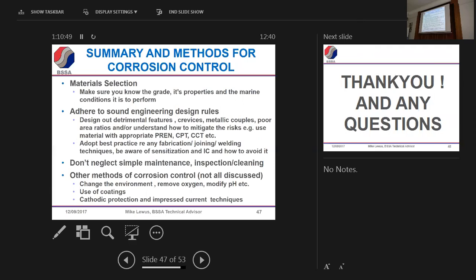The key thing with welding austenitics is, I didn't particularly point out at the beginning, but when I briefly showed you those atomic structures, the thing about a ferritic stainless steel is it's got a more open structure. Now, when you're welding, there's an advantage to having 5 to 10% of ferrite grains in the weld seam, because if your grains have things like phosphorus, silicon and boron, they can segregate to grain boundaries and form glassy phases there and make the weld very weak. A few ferritic grains mop up all these impurities that can form low melting point compounds. So there are some other caveats to go with welding austenitic grades.